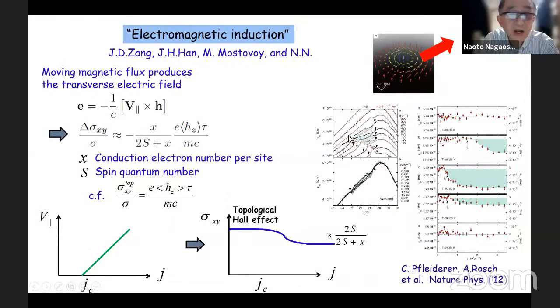So as for the motion, once the skyrmion begins to move, then the small E field is V cross H. H is also the Berry phase flux, gauge flux. And then this leads to the reduction of the topological Hall effect across the threshold current density like that. So this was our theoretical prediction. And then just after our theory, there appeared some German experiment which clearly shows the reduction of the topological Hall effect above the threshold current density. So this motion of the skyrmion leads to the emergent electric field perpendicular to the motion.